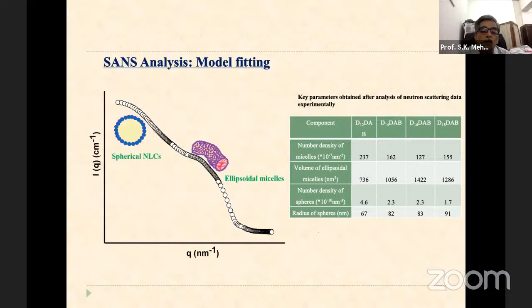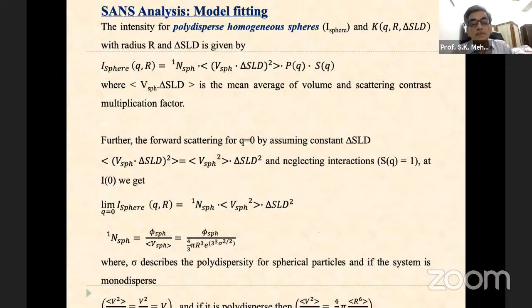So see, this is the overall picture she could develop. That initially we have spherical nanolipid particles, but as we move further, as concentration increases, you have ellipsoidal micelles. So this finding is very important, because when you are dealing with the system, what type of particle shape you require, or what type of particle size you require, you can manipulate your system if you know the prior information that we have the micelle formation or this type of shape formation using this type of concentration, and that can be very useful to you. So these are model fittings which I just skipped.